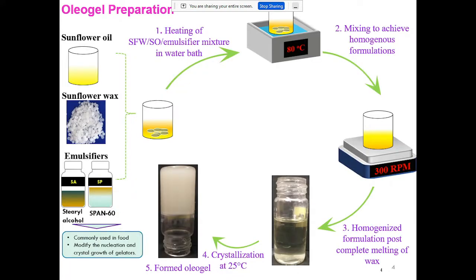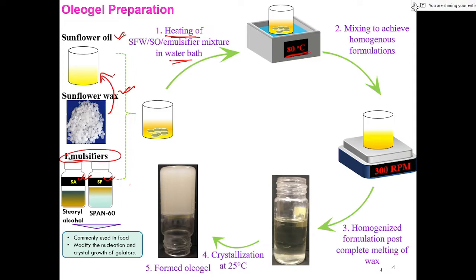Now the oleogel preparation, I told you, we mixed sunflower wax. To this sunflower oil we added the sunflower wax, and at the same time we added the emulsifier, stearyl alcohol or sorbitan monopalmitate. Then we heated it in a water bath at 80 degrees centigrade.